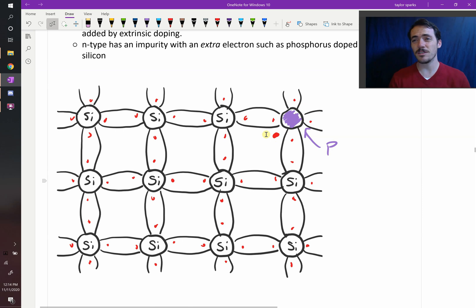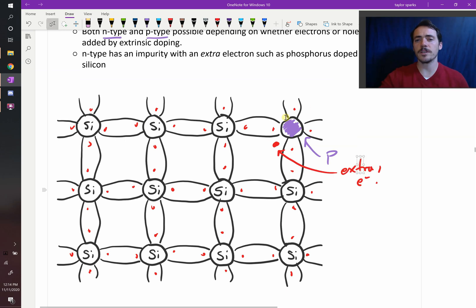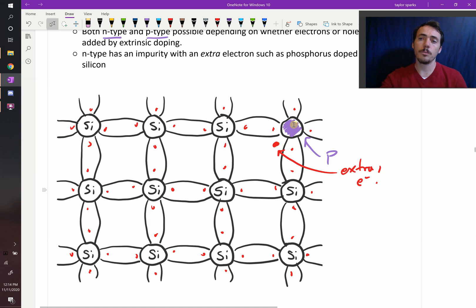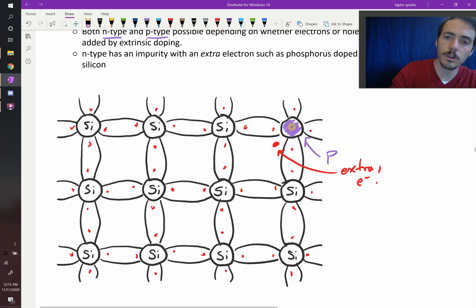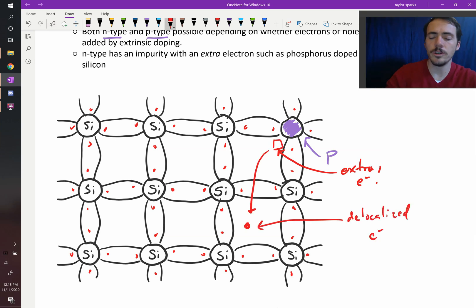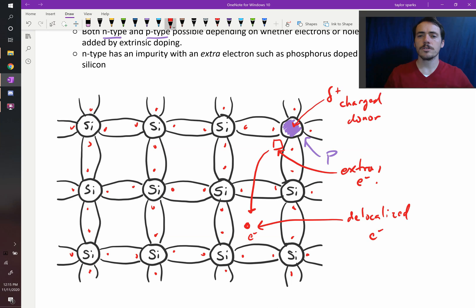This one electron is not involved in bonding — it's extra. The phosphorus isn't keen to have that electron because it's extra, but technically it needs it since phosphorus must have the same number of electrons as protons in its nucleus. If you took away this electron, you'd have a positively charged phosphorus, but that's a small energy penalty — smaller than stealing something out of a bond. Stealing it out of a bond is a big energy penalty, whereas making it a slightly charged donor of an electron is pretty small. So we've made a charged donor impurity.